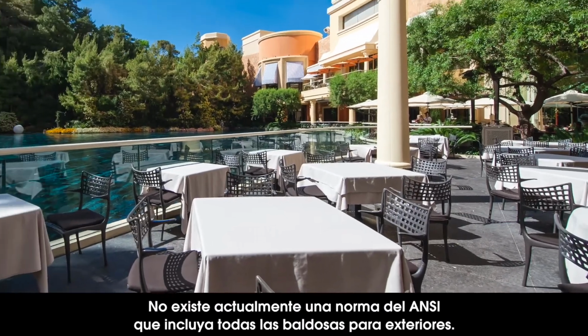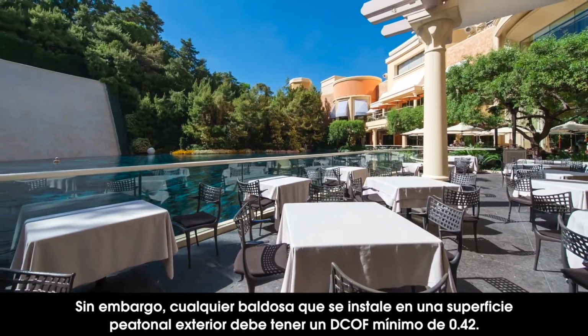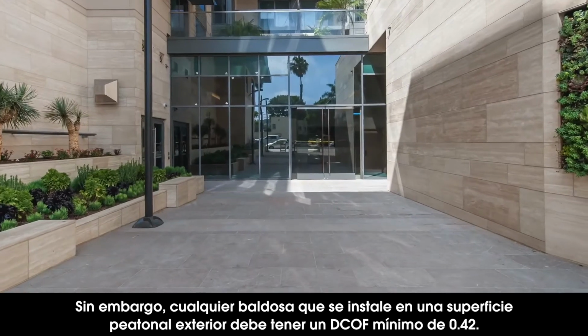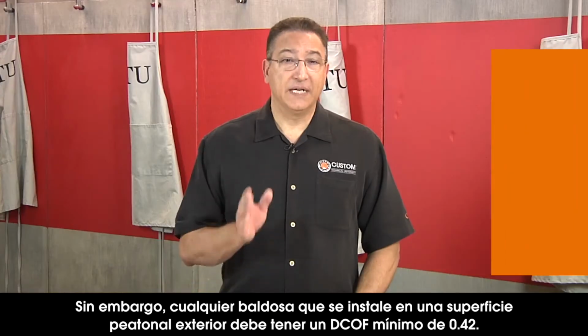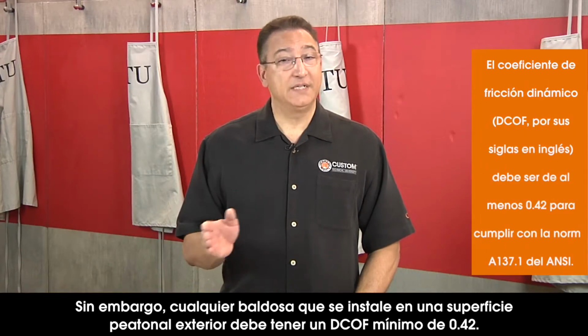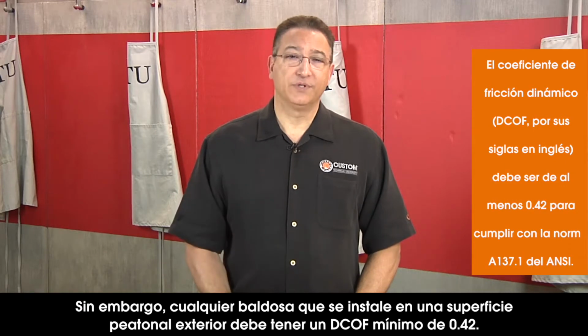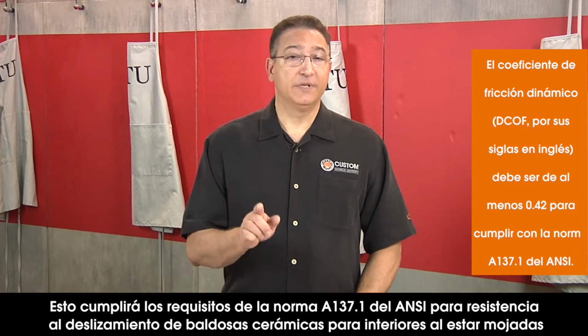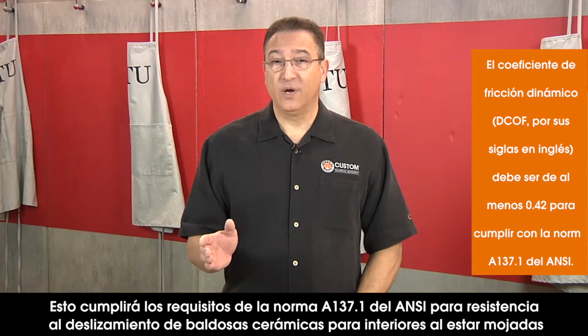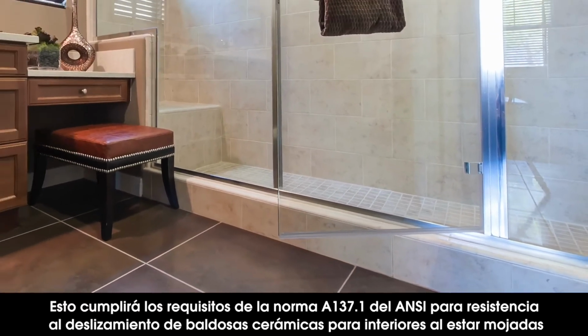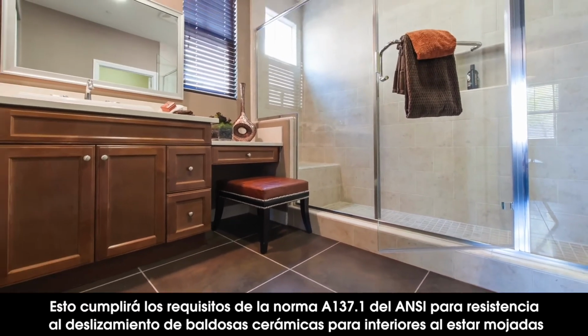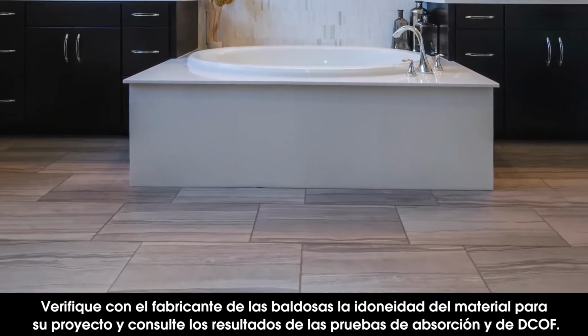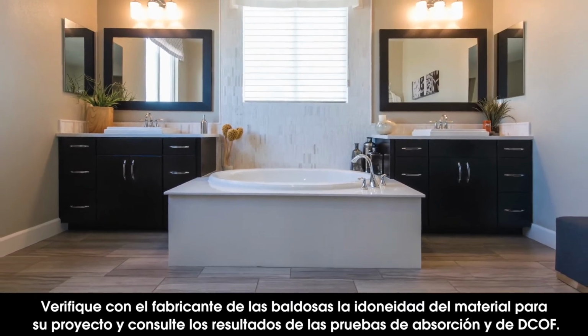Currently, there is no ANSI standard encompassing all exterior tiles. However, any tile set on an outdoor walking surface should have a dynamic coefficient of friction, or DCOF, of at least 0.42. This will meet the requirements of ANSI A137.1 for slip resistance of interior ceramic tile when it gets wet. Always check with the tile manufacturer about the suitability of the material for your project and consult the absorption and DCOF test results if they're available.